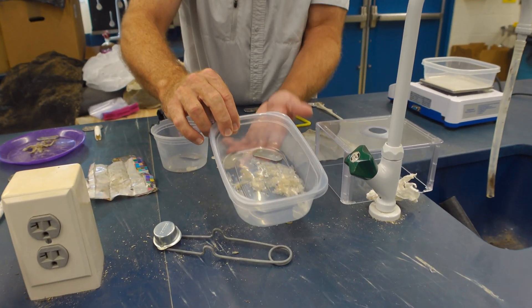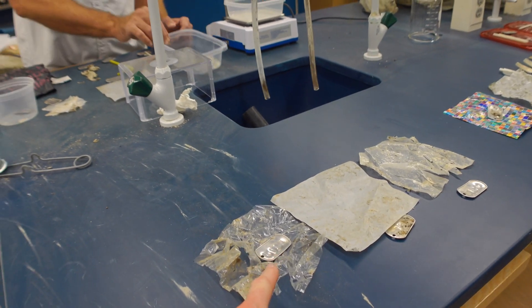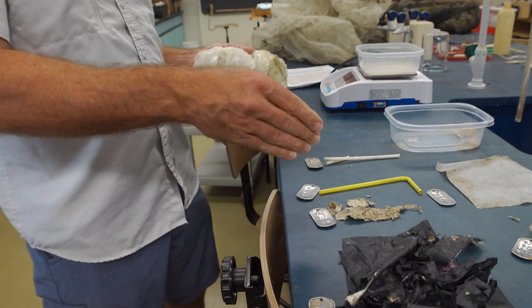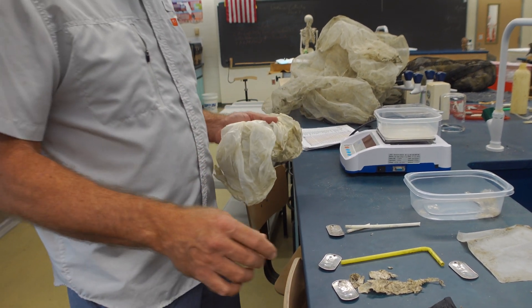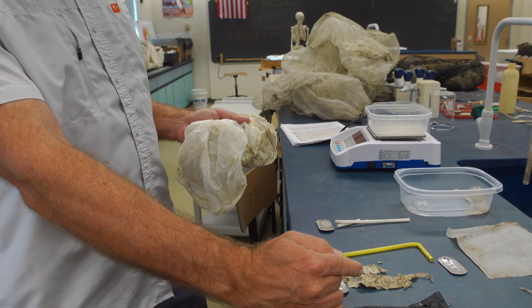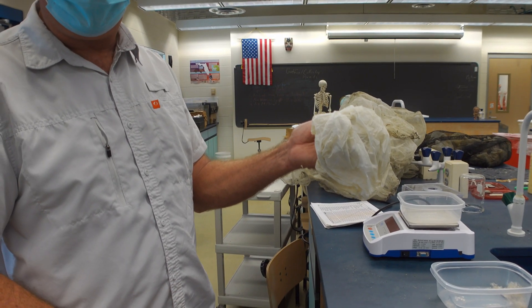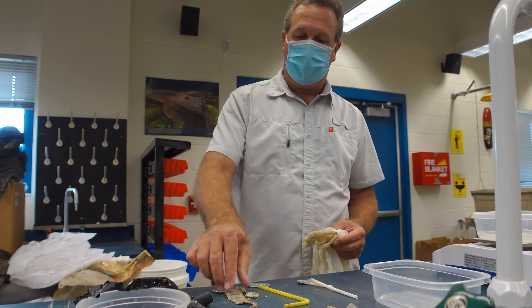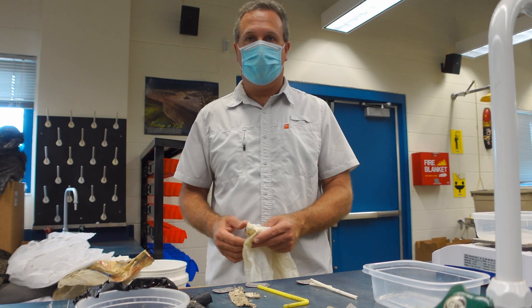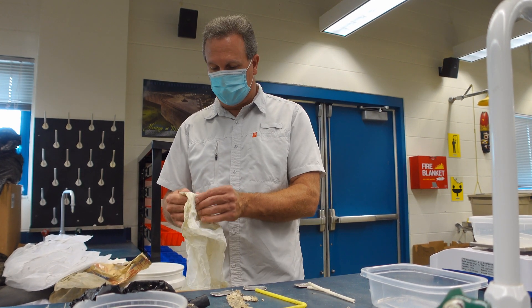This is the kind of thing we're seeing — Florida versus Maine. This was a strip off a PHA bag. This is at the eight-week time interval for Florida; this is at the 16-week time interval for Maine. So it's a remarkable difference. My water temp in Florida has been in the low 80s or above the entire time. Big, big difference.